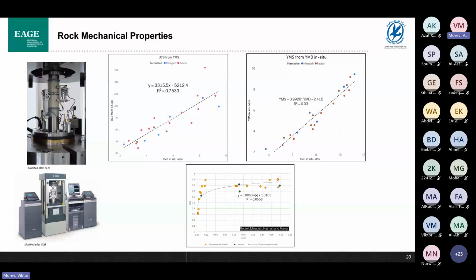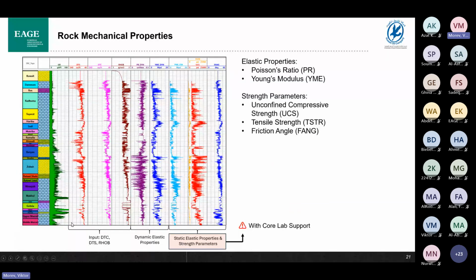I will give you an example. Here on the plot, you see the obligatory input logs for geomechanics, which are compressional and shear acoustic logs and the density log. From these logs, even without core studies, we can get dynamic elastic properties. But the next stage of getting static elastic properties and strength parameters requires core laboratory support and study of the core plugs. The strength parameters which we derived from the core laboratory equations are unconfined compressive strength, tensile strength, and friction angle.